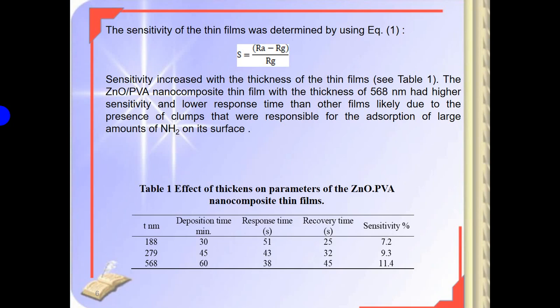The ZnO-PVA nanocomposite thin film with the thickness 568 nanometers had higher sensitivity and lower response time than the other films, likely due to the presence of clumps that were responsible for the adsorption of a large amount of ammonia gas on its surface. And this table shows the effect of the thickness on the parameters of this ZnO-PVA